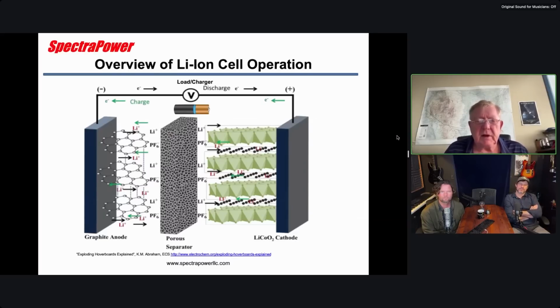Now, in both cases, these materials are coated onto the surface of a current collector. In the anode, that's copper, and I mentioned real thin copper foils, state of the art going from 6 to 4 microns. Wow! For people, that's like a tenth of a human hair. Very hard to handle. And on the cathode, it's aluminum foil, and that'll typically be more like 10, 12 microns thick, still quite thin. They're high purity foils. The copper foil is electrodeposited to make it, and I think the aluminum is probably rolled sheet.